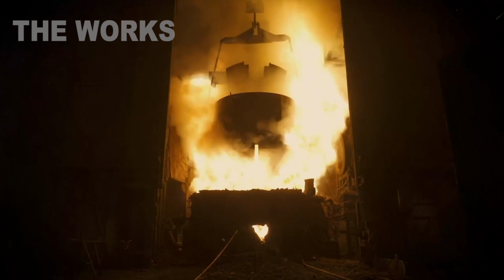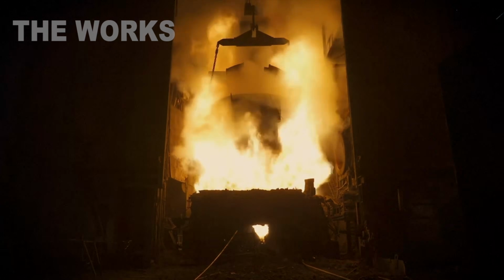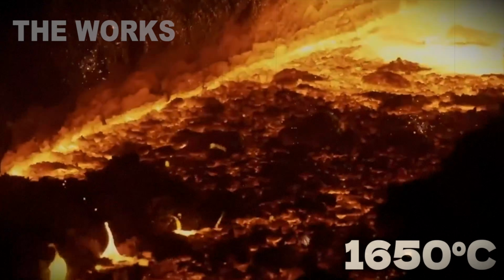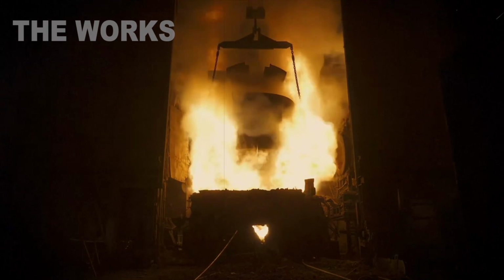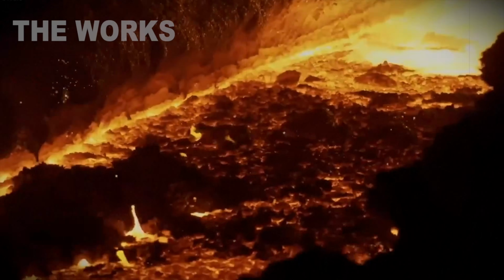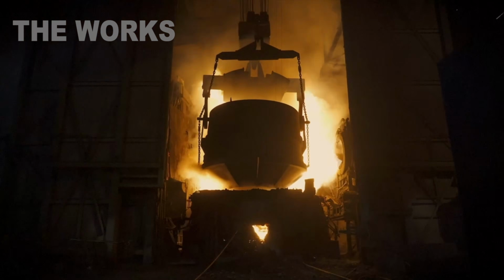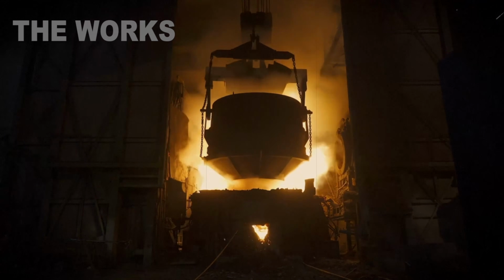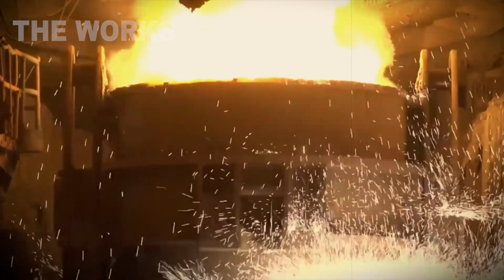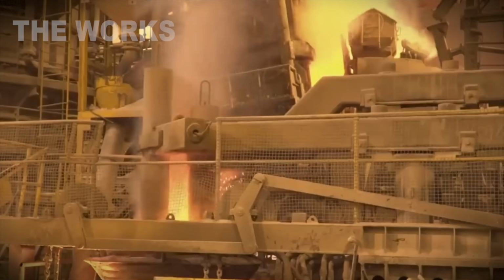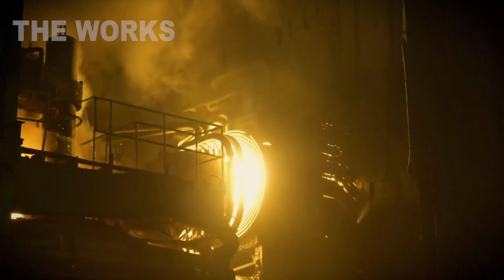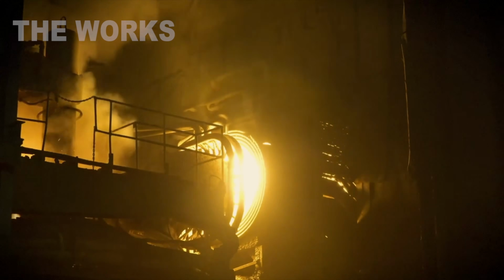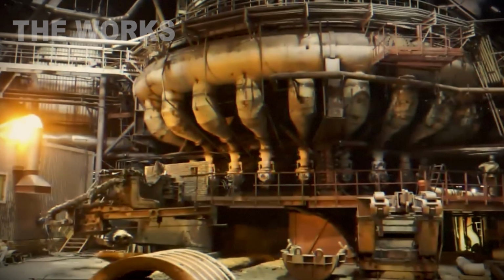Metal melts, becomes a liquid lake. The melt reaches 1,650 degrees. Melting time, 3 hours. Lab techs pull samples every 30 minutes, analyze composition on a spectrometer, adjust with ferroalloy additives. Precision matters: carbon tolerance plus or minus 0.05%, nickel plus or minus 0.1%.